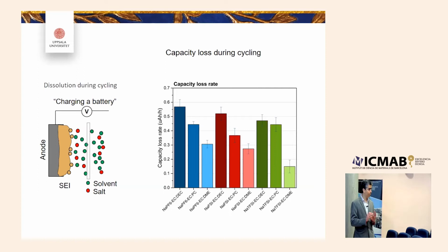Of course, this is one of the components, one of the aging mechanisms that we are focusing on. This doesn't necessarily mean that this electrolyte is the best electrolyte for sodium-ion batteries. Who knows what would happen if you put this electrolyte in a full cell with so many different aging mechanisms? Is this really stable on the cathode? We don't know. So the focus here is only on SEI dissolution. But this is a way to exclude at least some of the parameters from such a complex system and try to focus on one parameter or one aging mechanism.